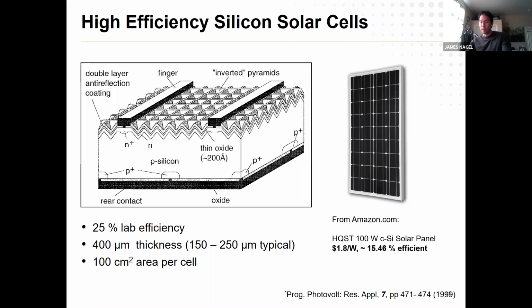And you get these little modules that are 100 square centimeters each, and they all have to be soldered together. I should also mention there's a slight barrier between what someone can do in a laboratory versus what you would even buy off the shelf. So I think it was like 2 years ago, I went to Amazon and just looked up high efficiency silicon solar cell, and that's the panel you could get a couple of years ago. It's a crystalline silicon, 100-watt solar cell, and you do the math on their pricing and the area, and you find it's about $1.8 per watt with a net efficiency of 15.5%.